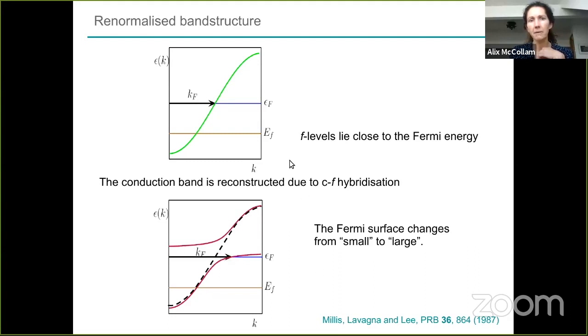So this is a change when you go from, say, high temperature, where you don't have the formation of these Kondo singlets, you don't have bound states and a coherent situation. You have regular band structure and a small Fermi surface, and then as you go to lower temperature and you get into the Kondo state, if you like, the Fermi surface will change from a small Fermi surface that doesn't include the f-electrons to a large Fermi surface that does include the f-electrons.